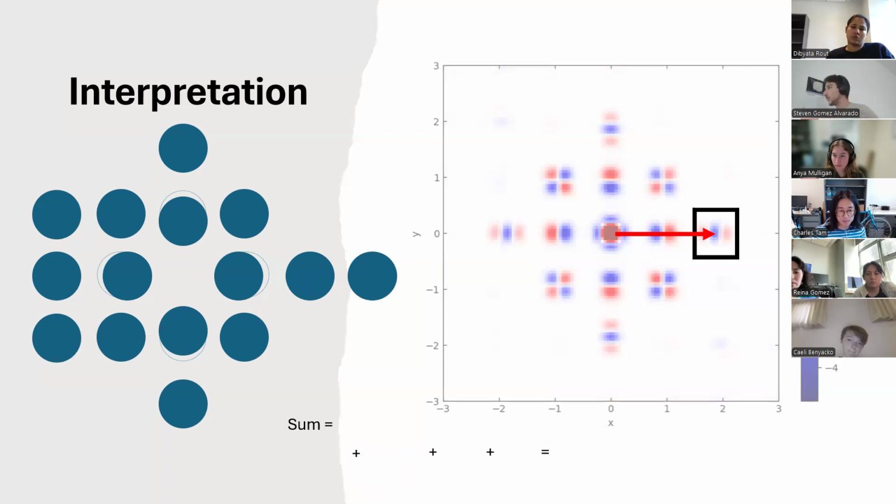So what's going on here? One of the most obvious correlations, which is 2 unit cells apart, is this one, where you have two atoms that were 2 unit cells away and they contract towards each other, right? Okay. So that contraction is going to be manifested as this dipole, okay? Where now the red intensity, the increase, is closer to the origin, right? It's to the left. So that represents electron density sort of shifting leftward towards the origin.